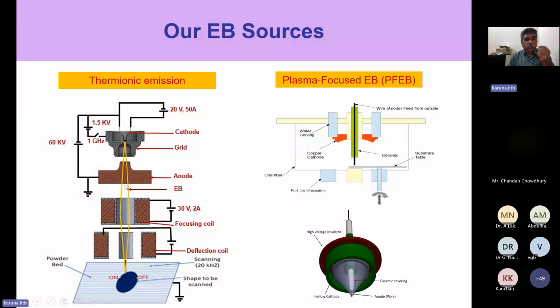When they escape through the anode, they reach something like 0.6 C. That means 50 to 60% of the velocity of light is reached by the electron. So they have a huge amount of kinetic energy available. When that goes very fast and hits the target, it creates a molten pool, melts the material. Now in between we have a lot of other things.